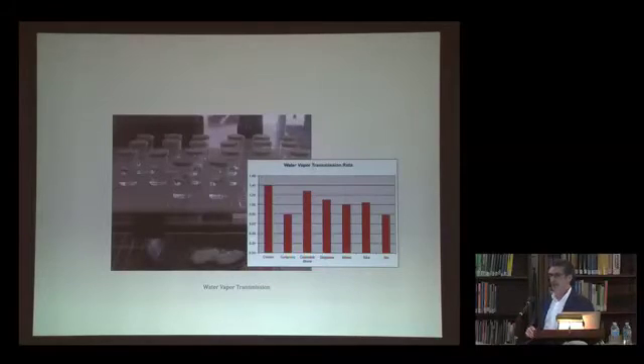transmission rate testing. We basically took samples of the cement, we took the coatings that I had shown you before, we put them into a vial with deionized water, and so the only way that this water could actually escape is through the whole sample, and all of them are put into an environmentally controlled tank, which is at a low humidity, and each one is weighed every 24 hours, and then the weight loss is basically based on the loss of the water, and then we can do a mathematical formula to calculate the water vapor transmission rate and then compare them to everything else.